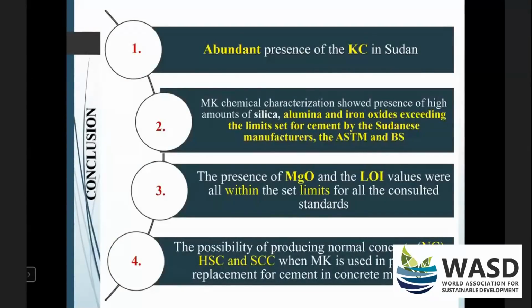So what can we say out of all these experimental work and results? The kaolinite clays are abundant, and they are present in different locations in Sudan. And that makes it one of the most important aspects. The other thing is that the chemical characterization of the metakaolin showed us the presence of high amounts of silica, alumina, and iron oxides. The percentages even exceed the limit set for cement by the 3 standards that we consulted.